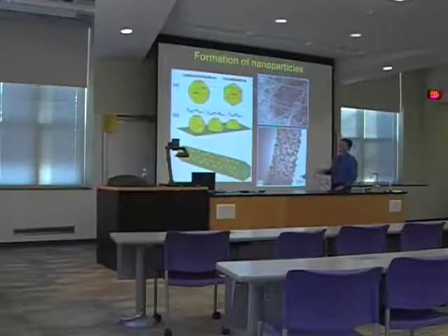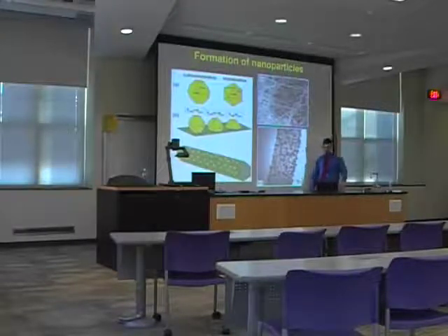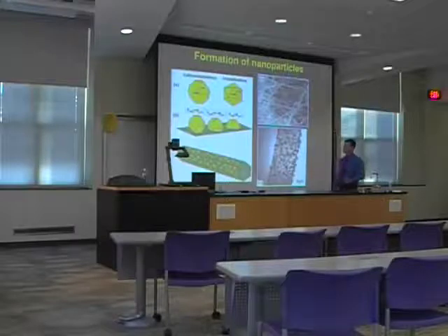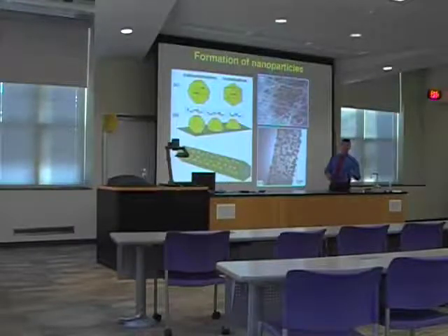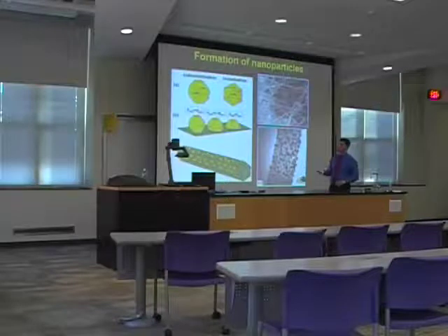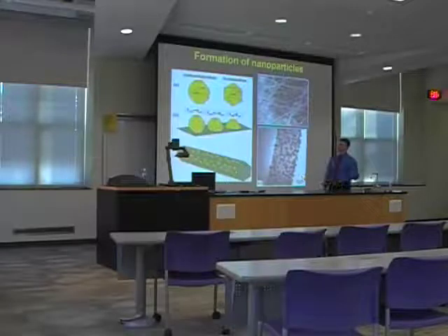So again, I would like you to think about that as a droplet on a hard surface. Normally a droplet on a hard surface takes spherical shape or shape of a spherical segment, depending on hydrophobic or hydrophilic surface. Here it's expressed in different terms, let's say adhesion energy and surface energy, but this is exactly the same process for the most part.